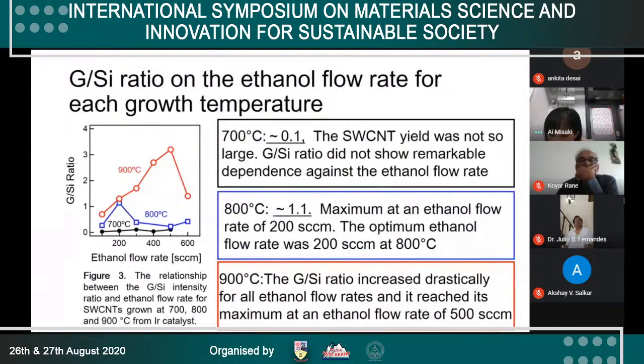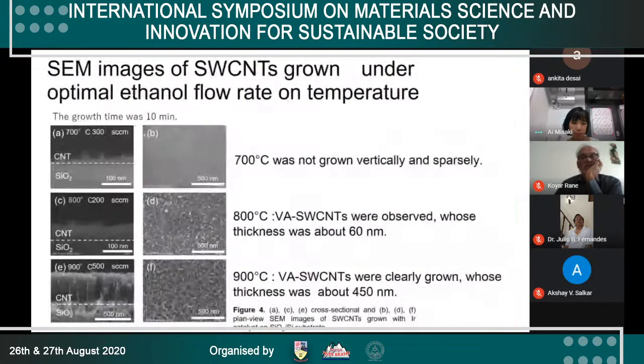When the growth temperature was 900 degrees C, the G/Si ratio increased drastically for all ethanol flow rates and reached its maximum at an ethanol flow rate of 500 SCCM. Moving on to the next slide, figure 4 shows cross-sectional and plane view SEM images of single-walled carbon nanotubes grown at 700, 800, and 900 degrees C for 10 minutes under the optimal ethanol flow rates for each growth temperature.